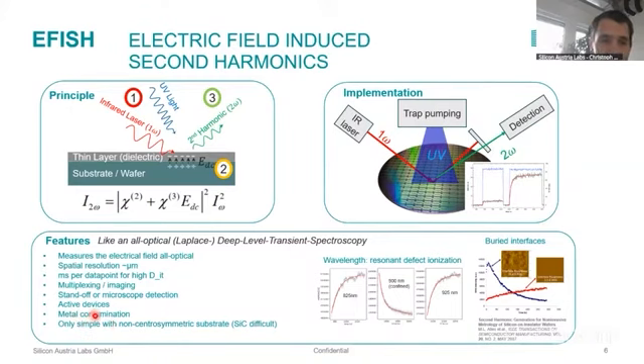Well, as I already said, active devices, you can sacrifice resolution for working distance if you want to measure an environment where you cannot go that close to the wafer for other reasons, because maybe it's in a process and you need access for other things. What is a bit difficult, but it's not a total showstopper, is non-centrosymmetric substrates like silicon carbide. So then you get a large bulk second-order nonlinear susceptibility, and you have to disentangle this from the E-fish signal here.